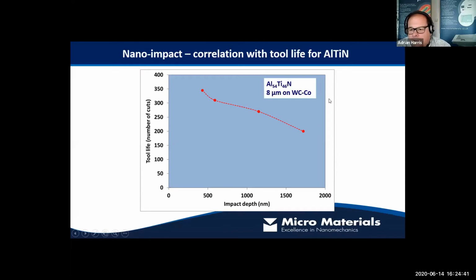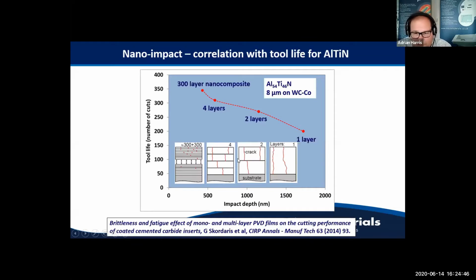So what I'm looking for, the morphology of the coatings is different. So this is how they're different. This sample here, the one that gives the best tool life and the smallest impact depth, is actually a nano multi-layer coating. So there are 300 plus layers in this coating. Okay, they're all aluminium titanium nitride. One layer's been put down, then another, then another, then another.